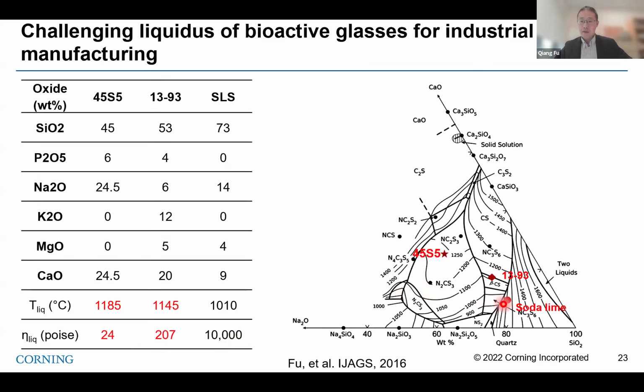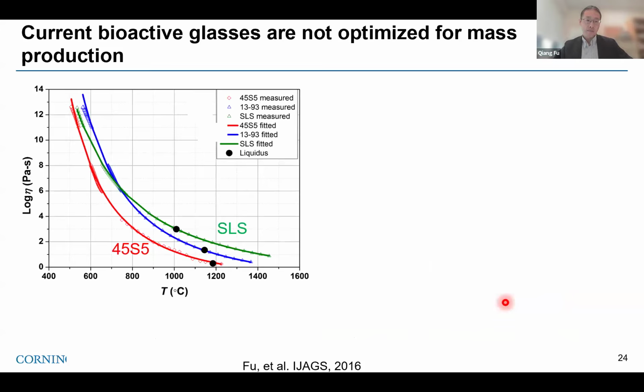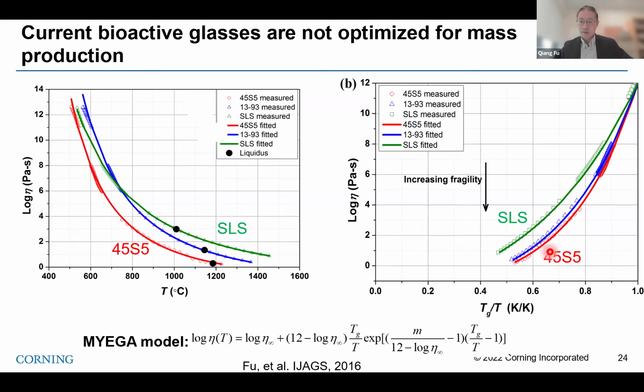One reason behind that is soda-lime has high silica, which helps lower the liquidus temperature and also raises the viscosity. All this helps make soda-lime much easier for mass production. Another big challenge is the fragility of the glass. If you look at viscosity versus temperature, the high temperature viscosity curve of soda-lime is much flatter, while for 45S5 and 1393 you can see sharp changes in viscosity with temperature. The fragility index of this bioglass is also much higher. Compared with soda-lime, with 45S5 and 1393 you can see increasing fragility across the different glass compositions. We use the Mauro model to fit this viscosity data in order to get the fragility of the glasses.